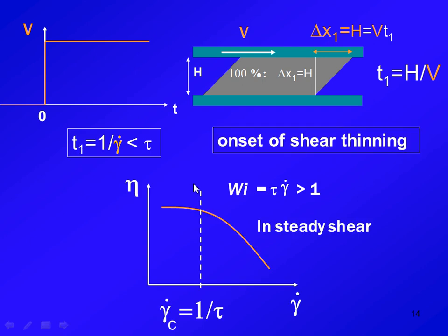In particular, polymer scientists all know shear thinning. The moment shear thinning occurs, that is, the viscosity starts to become lower with respect to the rate of shear, is precisely the point where making 100% deformation will take a time as long as tau. But we are always interested in processing faster and faster. Therefore, we're always in the regime where the time it takes to make large deformation is negligibly small. And then, obviously, you ask yourself, what happened to that ball of rice noodles when you do it that fast?